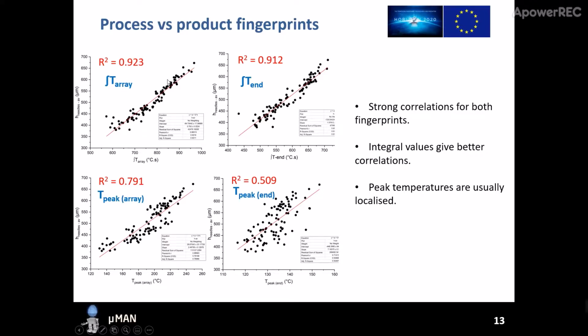from regions of interest from the 6x6 array and towards the end of the cavity. And as you can see, these scattered data give us very good linear relationships between the average needle height, which is on the y-axis, and our product fingerprint on the x-axis. So we could say that integral values are quite good process fingerprints that could tell us about the microreplication quality of our microneedles. And these R-squared values are quite good, and this represents the goodness of the linear fit to this scattered data, and values of 0.9 for R-squared are quite good for a linear fit, and we have seen strong correlations for both fingerprints.